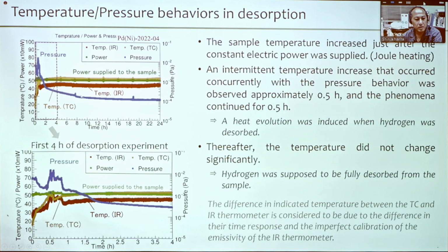So this yellow plot shows the temperature measured by the thermocouple, and red one is measured by the IR thermometer, and this blue line shows the pressure inside the chamber. Then this green one is the supplied power to the sample. So now the supplied power is constant. So you can see some periodic fluctuation of the supplied power, but we have understood this. This is due to the noise of the logging system, not the real electric power fluctuation.